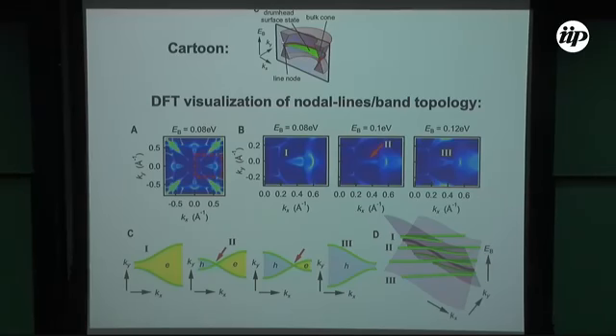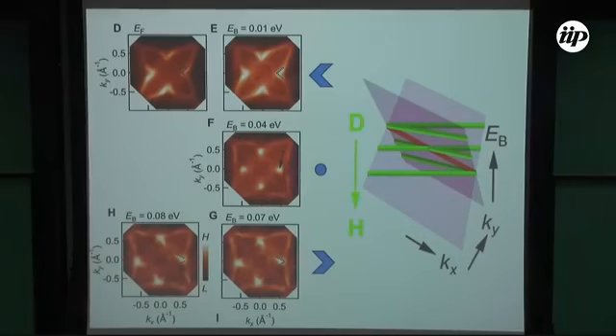So what we are looking for is a nodal line like this, where on each node there's a Dirac point or a Weyl point. Either one will do. Since these are topological objects, they're connected on the surface. So these surface states will create some sort of drumhead-like states, which has been conceptually put forward. Then, as I said, we searched the materials database and found materials that fit the bill. It's not exactly what we're looking for, but something close.